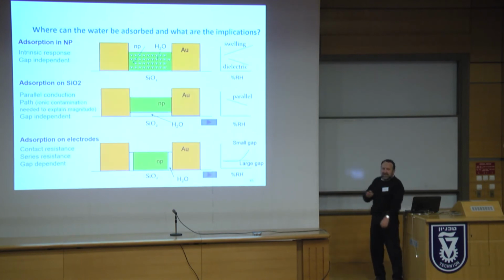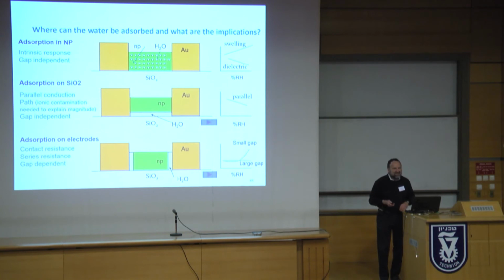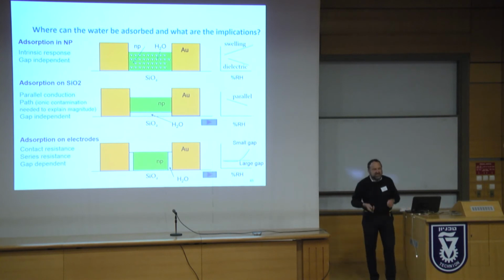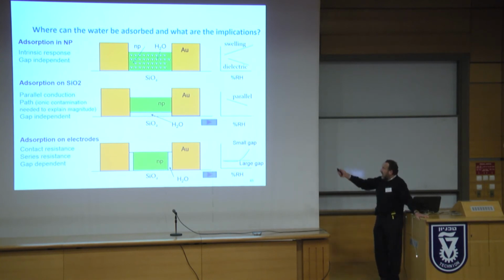Now, I can explain the phenomenology this way. If water is absorbed in the nanoparticles itself, it simply changes the resistivity. This shouldn't reflect any gap effect. The same thing if the water is absorbed underneath, you get simply a parallel path of conductance, so the resistance should go down. However, if the water is absorbed on the electrodes themselves and somehow causes the resistance to increase, you will get an increased resistance.